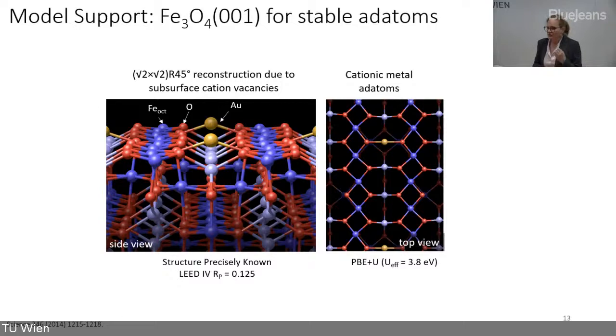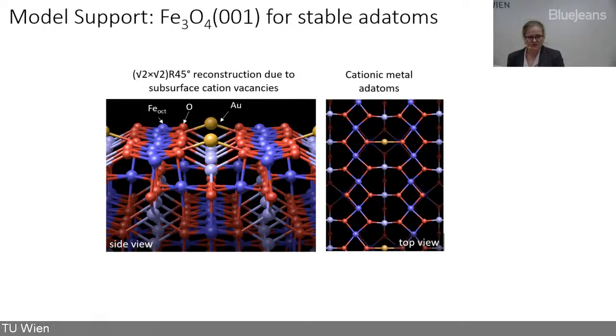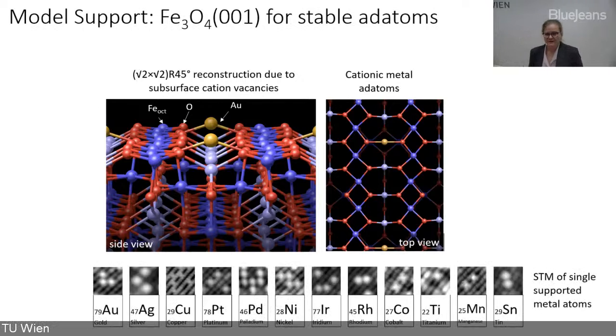Now it turns out this is not only true for gold, but Gerhard and his friends went pretty much across the periodic table. They were very busy and put essentially all elements they could find, and for each and every one of them, you could see single atoms at especially this site. That's a really wonderful model system, and we understand why. We can put and place single atoms on a well-defined support.